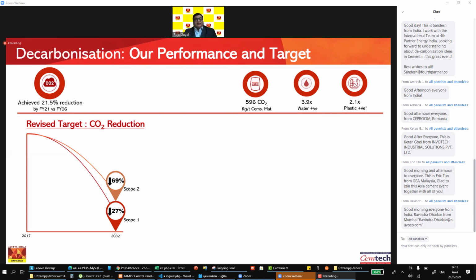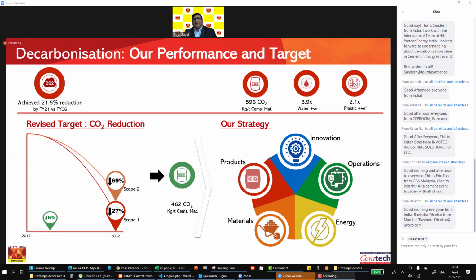Our commitment is to reduce scope 1, which is the direct emission, by 27% by 2032, and indirect, which is scope 2, by 69%. Baseline of 2017, out of the 27%, 6% has been achieved so far. This will be translated into 462 kg CO2 per ton of cementitious material. To achieve that, we have a 5-pillar strategy, which consists of operations, energy, materials, product, and innovation to achieve our ambition for the